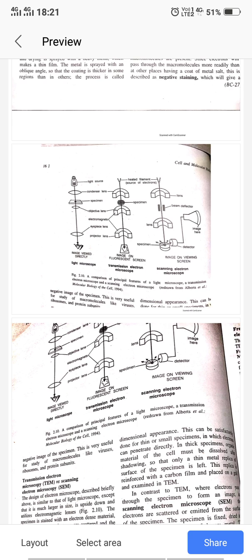In contrast to transmission electron microscopy, where electrons pass through the specimen to form an image, in scanning electron microscope, the electrons are scattered or emitted from the surface of the specimen. The specimen is fixed, dried and coated with a thin layer of heavy metal. This specimen is then scanned with a very narrow beam of electrons. The quantity of electrons scattered or emitted from each successive point on the metallic surface is measured and used to control the intensity of a second beam, which moves in synchrony with the primary beam and forms a highly enlarged image on a television screen.